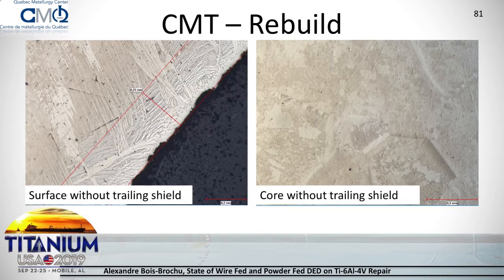And since your machining requirements will be greater than that, you can work without a trailing shield in some applications, and you don't need to be fully in atmosphere when you're using DED with wire. And in the core, there was no significant oxygen pickup in this case without trailing shield. And we can see, well, we cannot see it very well in this case, but there were no alpha colonies growth over there, and there was no oxygen pickup. So you can, in some applications, work without trailing shield at all.